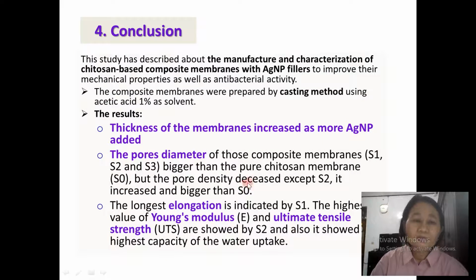We come to the conclusion. This study has described the manufacture and characterization of chitosan-based composite membranes with silver nanoparticle filler, to improve their mechanical properties as well as antibacterial activity. The composite membranes were prepared by casting method using 1% acetic acid as a solvent.